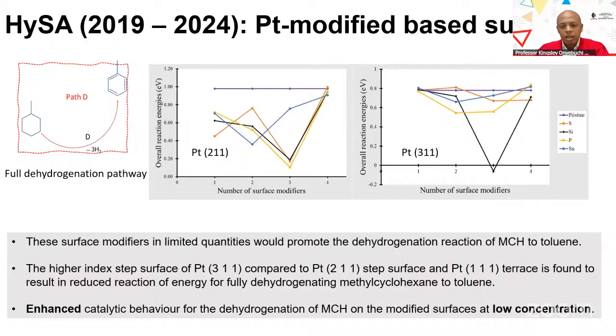So we reduced our loading, and I'll go to the end and show you the full dehydrogenation pathways, removal of the hydrogen here. You can see for the different surfaces we considered, this is the pristine surface, and then you have the different surface modifiers. You can see generally for low concentration of modifiers, it's good. But as you increase the concentration of the modifiers, you have almost similar activity. So it tells us that at low concentration, these catalyst poisoners can actually act as catalytic enhancers and modify the surface of our catalyst.